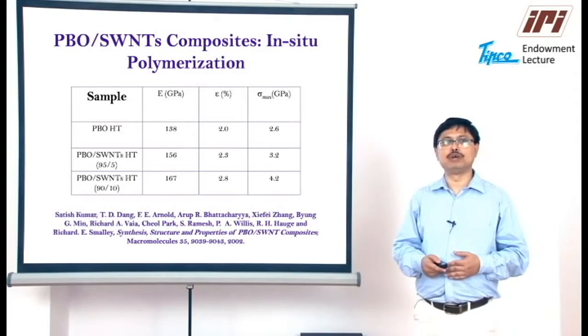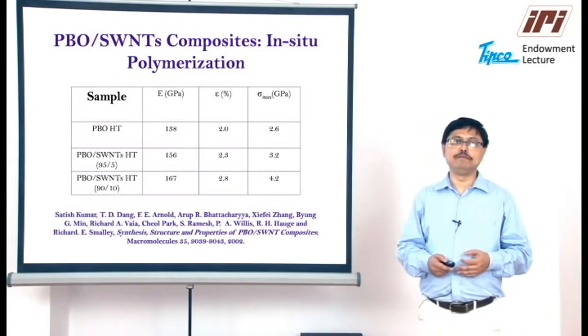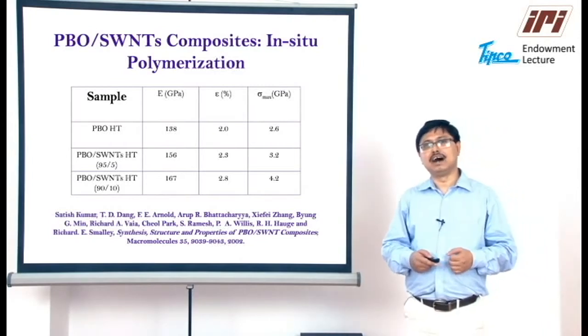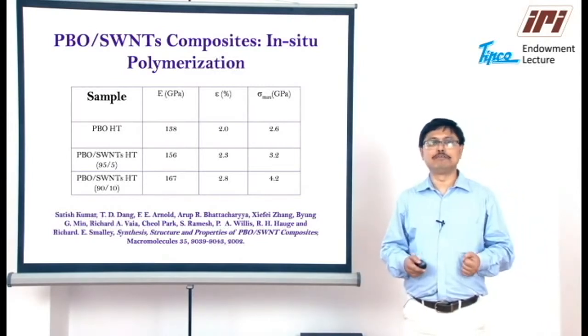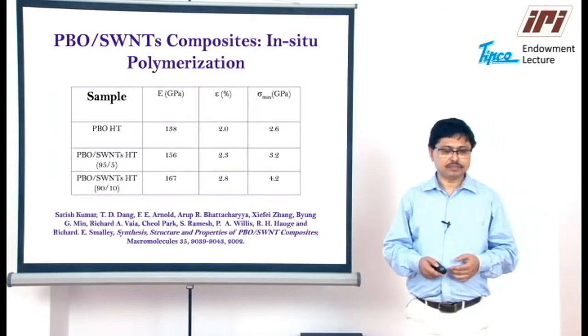These composites were prepared during the in situ polymerization of the PBO, and later on were heat treated in an argon atmosphere in a tubular furnace in order to make them more oriented.